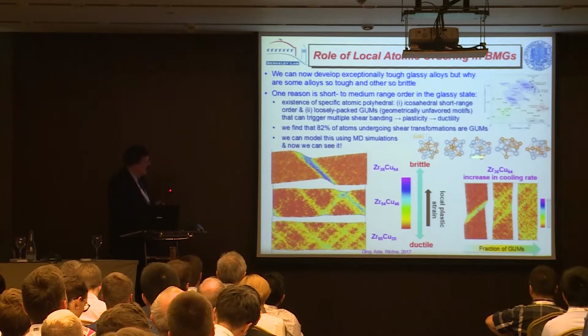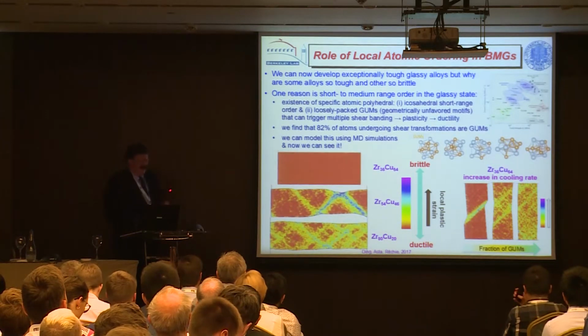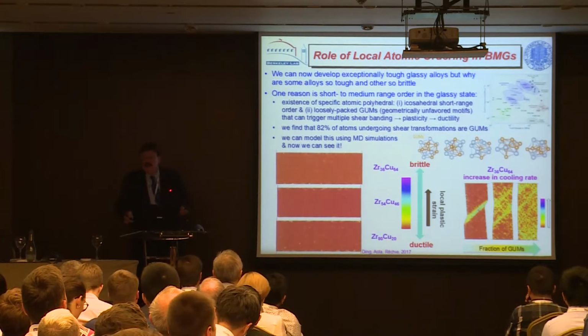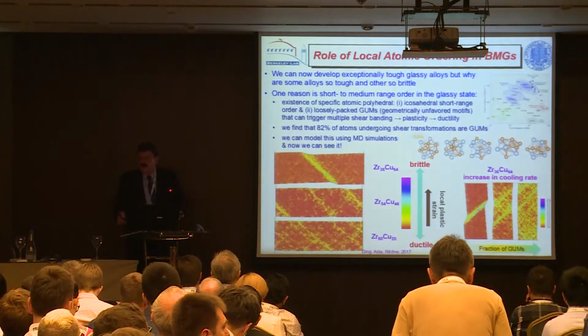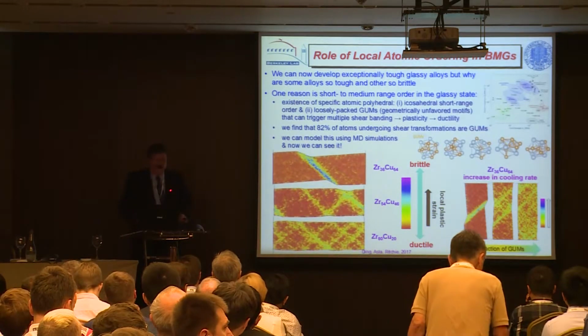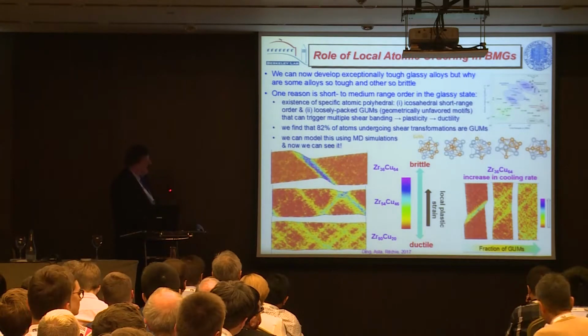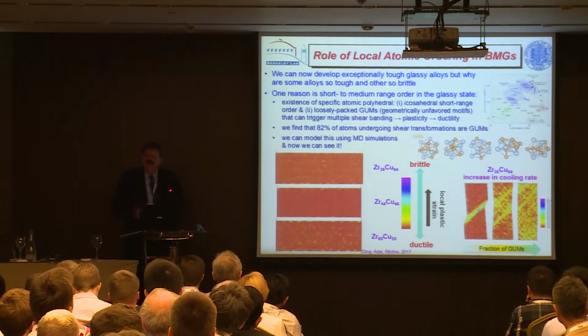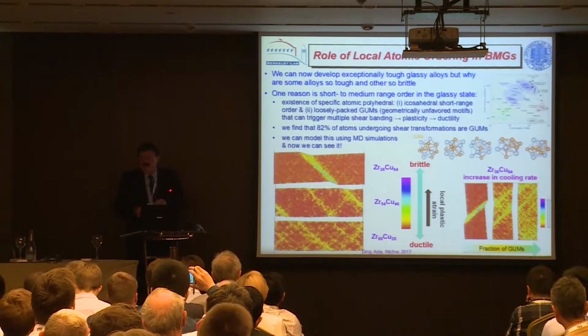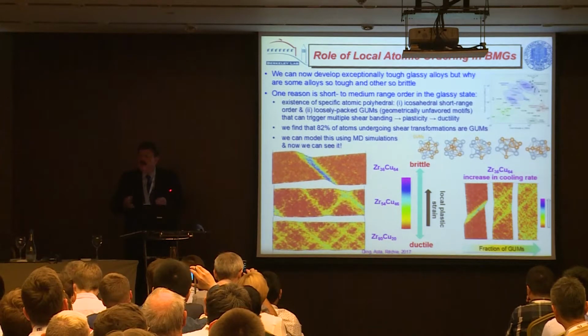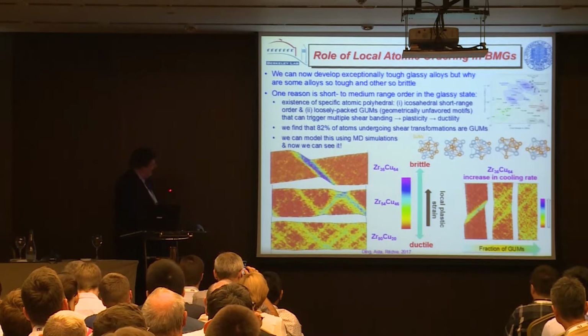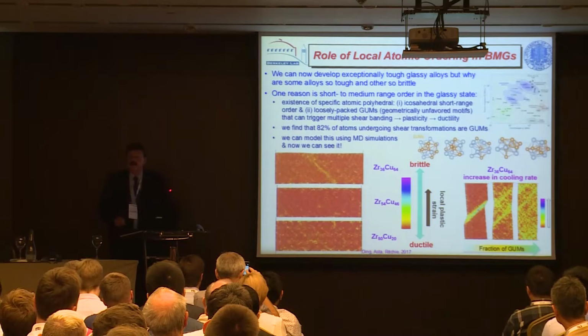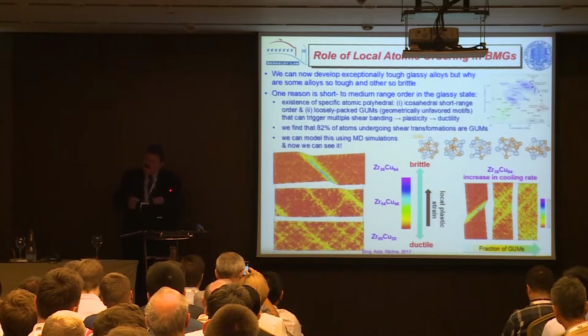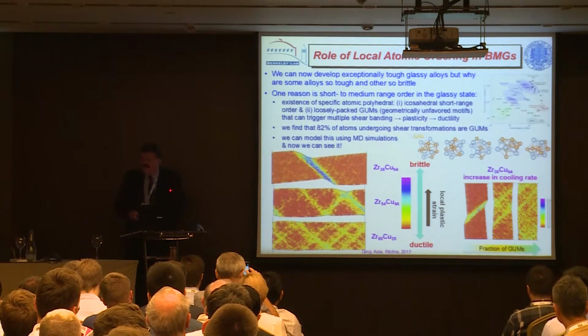And most of the most stable forms of these kinds of motifs have icosahedral symmetry. They have five-fold symmetry, and they're generally most stable. But there are some configurations that are not as tightly packed, that don't have as much icosahedral symmetry, and these tend to be relatively unstable. And Evan Maher has coined the term geometrically unfavorable motifs, GUMs. And these are local order which is not quite as stable.